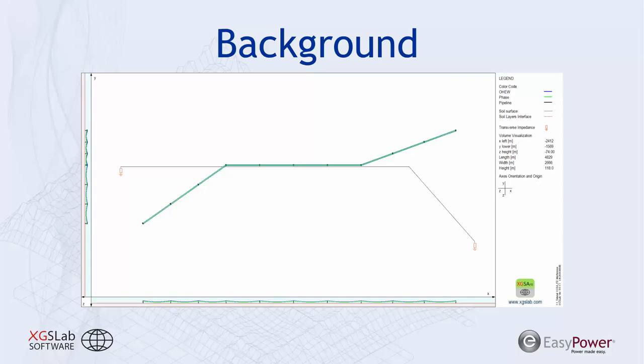of the pipeline. Also, one thing I want you to see is that XGS Lab is incorporating the sag of the transmission line, as you can see on the XZ plane here and the YZ plane. So it's a very accurate analysis. And another thing to help with that accuracy is we have a portion of the pipeline, or the end of each pipeline, has a Thevenin equivalent of that pipe extending on for infinity. And what this does is it allows the modeled space to be relatively small while not allowing any sort of end effects in your analysis.